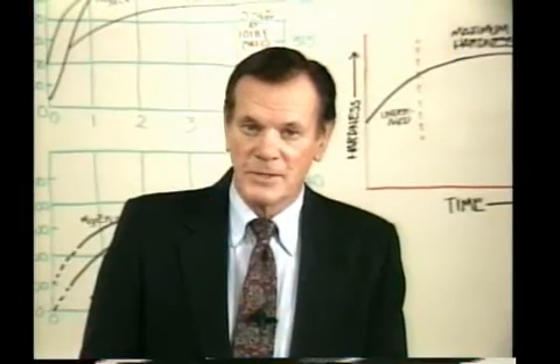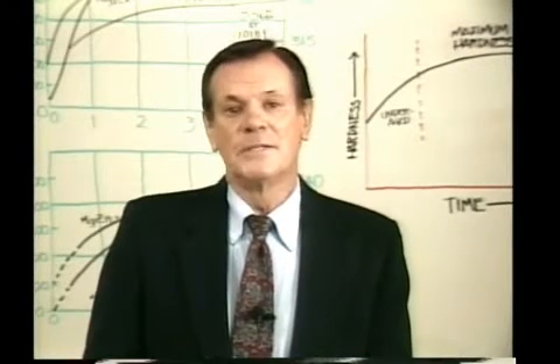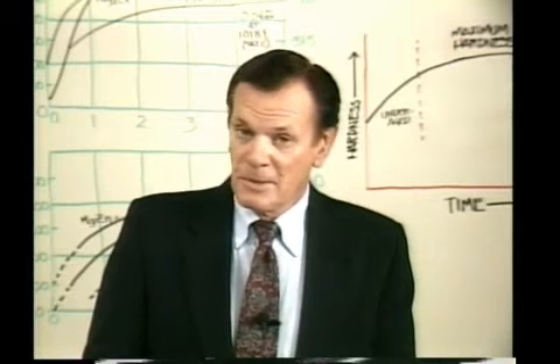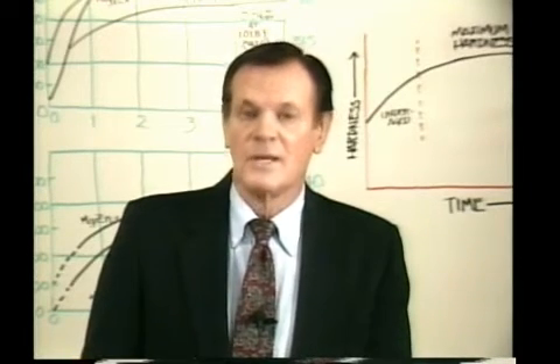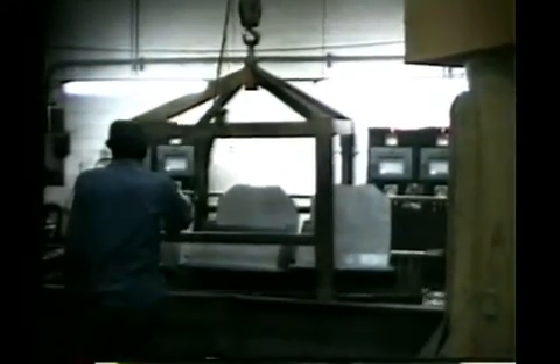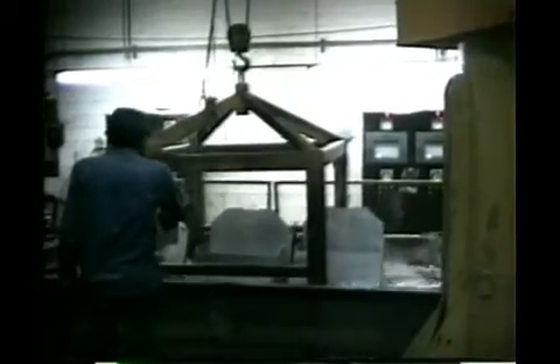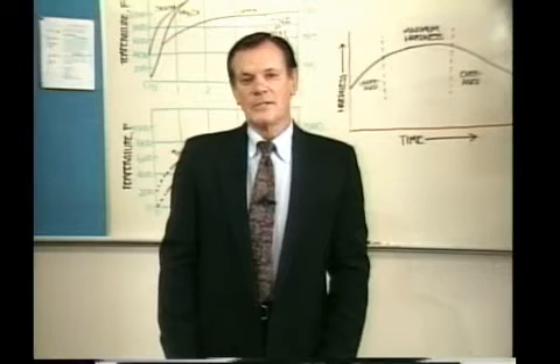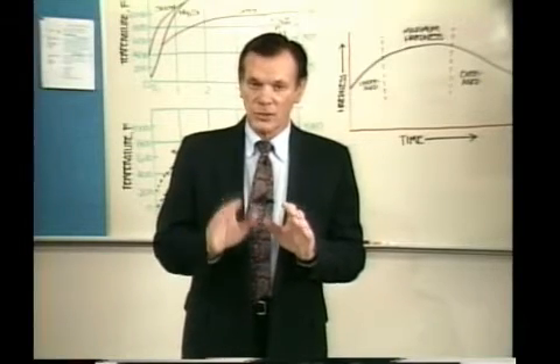The speed at which the atoms diffuse depends upon the temperature of the part and the type of material being heat treated. In some materials, such as precipitation hardening steels, the diffusion reaction is very sluggish. That is, the atoms move very slowly. Thus, the quench necessary to retard this diffusion and freeze the lattice need not be too severe. In aluminum alloys, however, this diffusion is extremely rapid. Therefore, an extremely rapid quench must be used in order to freeze the atoms in place. A rapid quenching medium, such as water or a water polymer solution, is normally used to quench aluminum alloys. The basic principles of quenching apply to other metals as well as aluminum alloys.